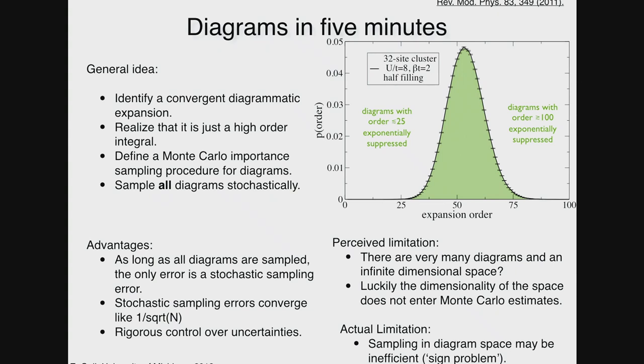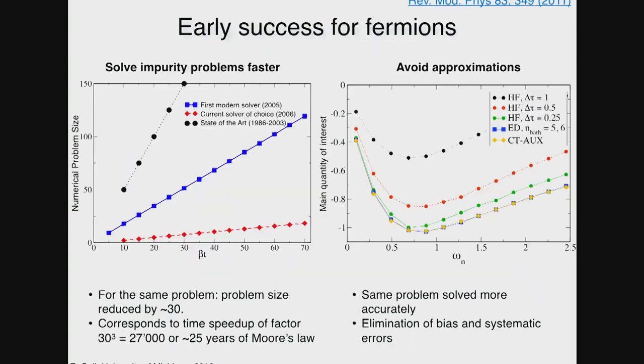You have some terms that are positive, some terms that are negative, and your signal disappears in the noise. So a lot of effort is actually spent in reformulating series in such a way that they have mostly positive or positive expansions. Now, let me show here early success that we had in simulating these methods for fermions. What you see over here is the typical numerical problem size that we had in these methods as a function of inverse temperature here. This is a single-site dynamical mean field calculation at a U of about the bandwidth. Details here are not that important.